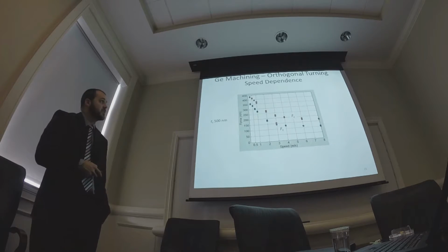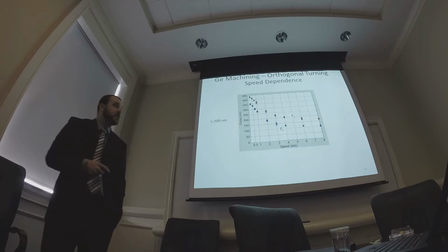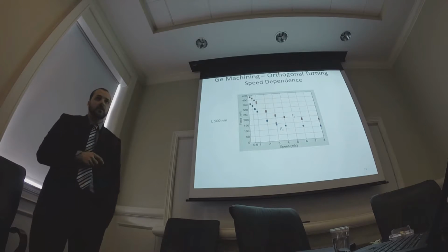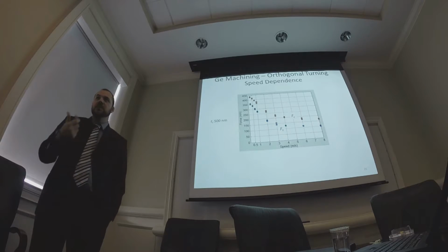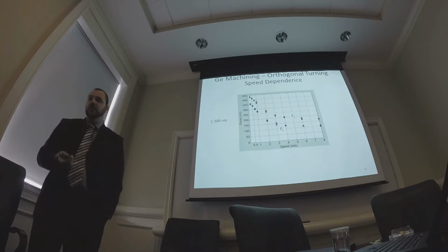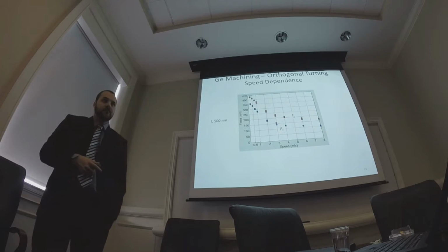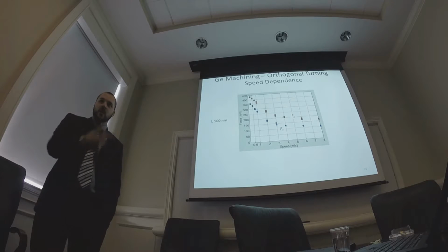So we said, okay, let's try a different chip thickness - here's 500 nanometers, and again the same thing. So it seems there is a speed dependence in germanium. We did the calculation for what amount of energy put into the surface could potentially melt germanium, and the numbers were surprisingly similar if we assumed 20% of the heat stays in the chip and 20% of the force put into the surface causes heat in the chip. We were getting numbers around the melting temperature of germanium.